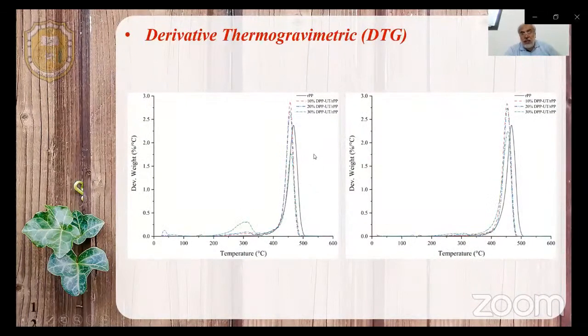So for the recycled, actually we see here a reverse trend. There was no improvement in the thermal stability because the shift was to the left.